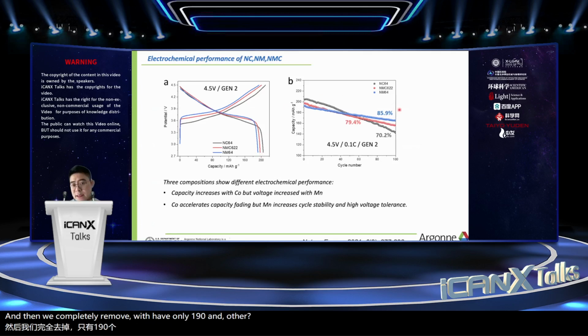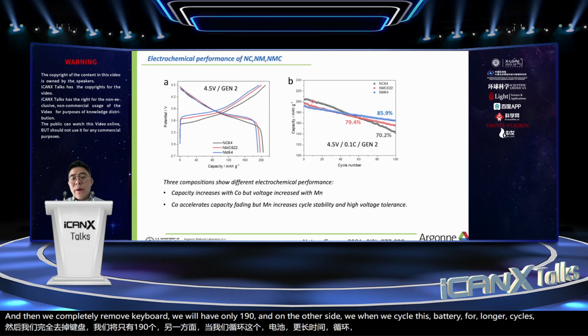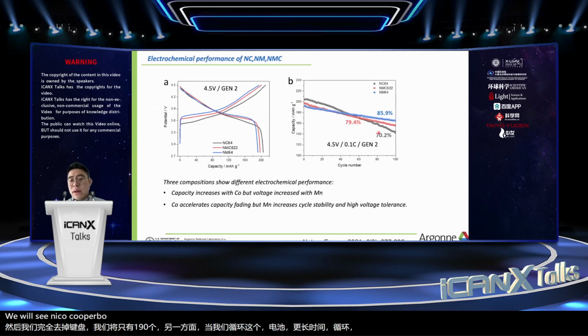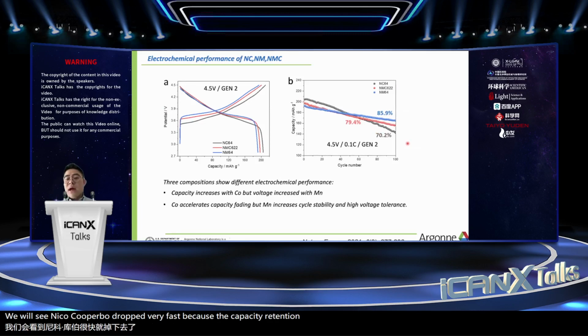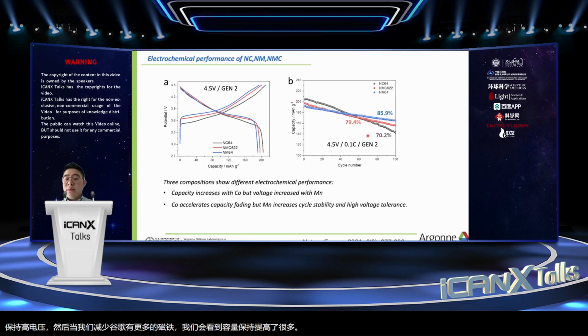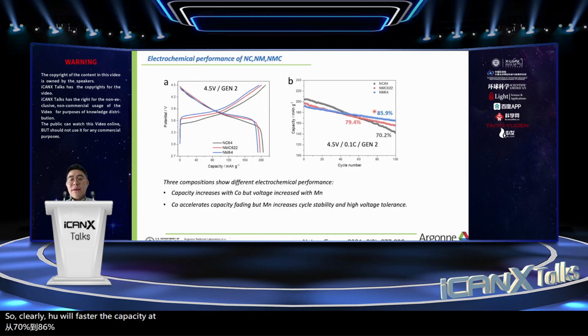And on the other side, when we cycle this battery for longer cycles, we will see nickel cobalt dropped very fast because the capacity cannot be kept at the high voltage. And then when we reduce cobalt to have more manganese, we will see the capacity retention improve a lot, right? From 70% to 86%. So clearly, cobalt will accelerate the capacity fading, and manganese can stabilize the electrochemical performance.